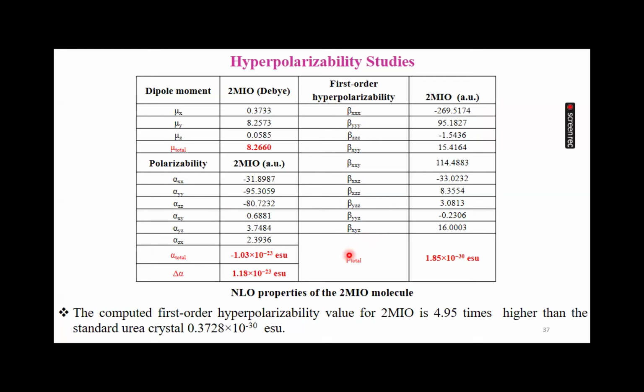The computed values of the dipole moment, polarizability, anisotropy, and first order hyperpolarizability for the 2-MIO compound were found to be 8.26 Debye, alpha total 1.03 times 10 to the minus 23 esu, and beta total 1.85 times 10 to the minus 30 esu. The computed first order hyperpolarizability value for 2-MIO is 4.95 times more than the standard urea crystal. The 2-MIO compound's NLO properties confirmed it as an NLO crystal.